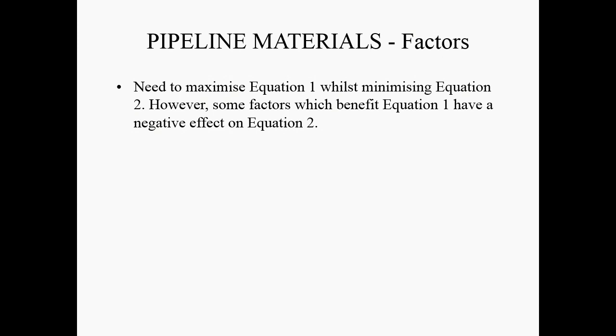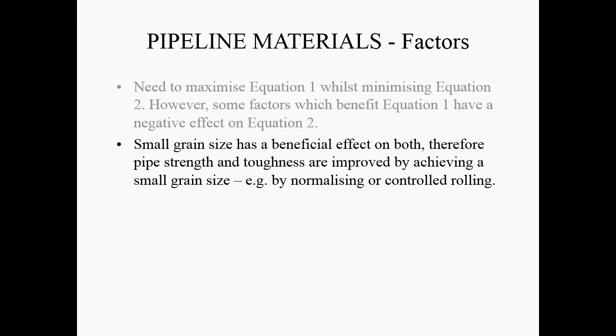So we maximise equation 1 by minimising equation 2, and we want the factors that benefit equation 1 having a negative effect on equation 2, and that's the small grain size. So pipe strength and toughness are improved by achieving a small grain size by normalising or controlled rolling. So if we can achieve the strength and toughness we require without adding alloying elements, we also can do that without sacrificing weldability. So this is like the holy grail for the pipeline industry. We want to have strength, toughness and weldability.